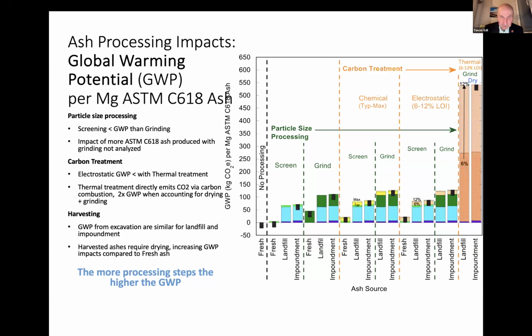So this picture shows you the greenhouse gas generation per ton of this fly ash produced. And at the bottom, you see fresh, landfill, impoundment. There's the source of fly ash. As you can see with fresh, there's hardly much of anything, but landfill, a little more, impoundment, a little more things involved because of the high water content. And then there is grinding and then the carbon treatment, which involves screening and grinding and then doing chemical, electrostatic, and thermal type of effort.